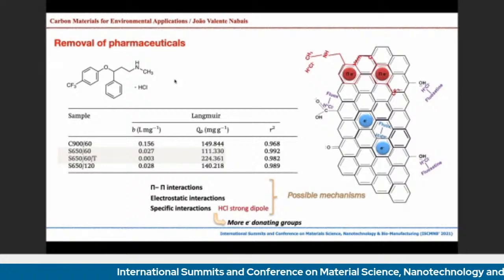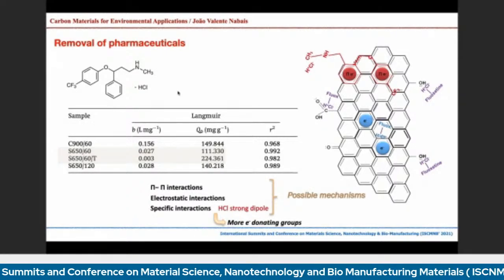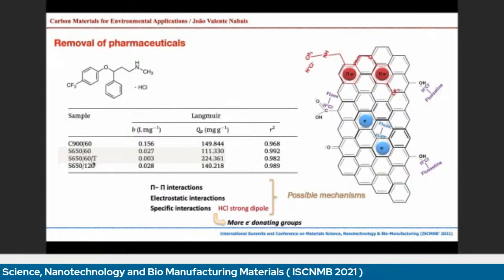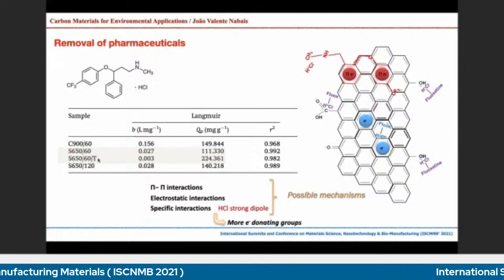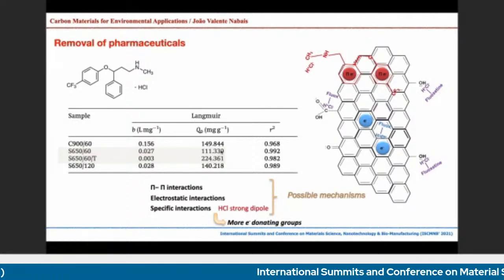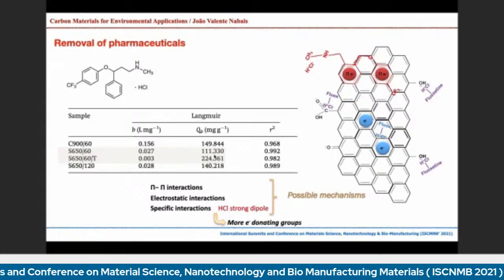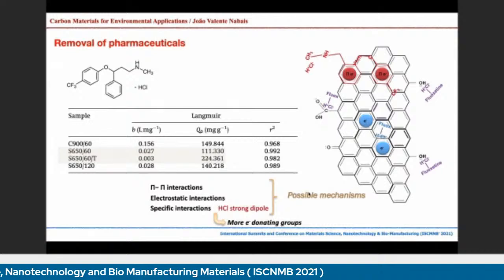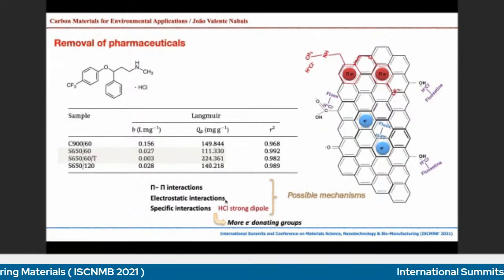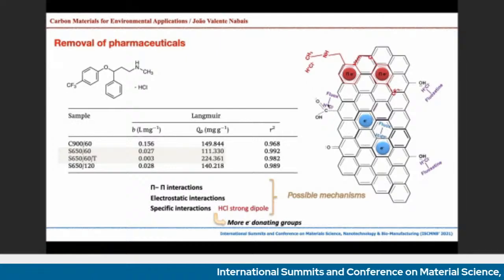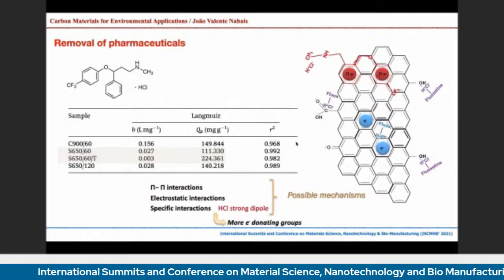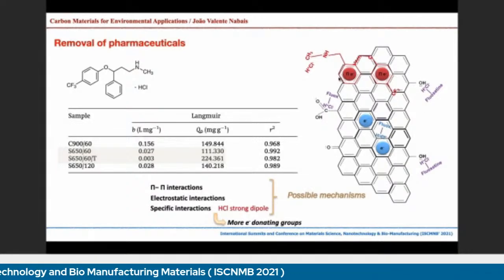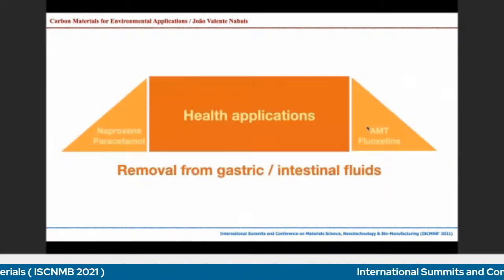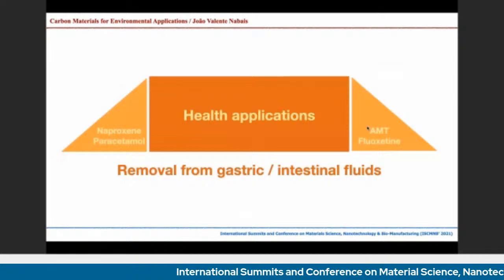When it comes to the fluoxetine, which is the principal type of Prozac, as I told you, you can see here again this T means that the material was impregnated with tether. Again, the absorption of fluoxetine has doubled. So again, the use of tether for doing the post-modification of the carbons is quite beneficial for the absorption. Here, the possible mechanisms are the pi-pi interactions, some electrostatic interactions, because fluoxetine has this group here which has a charge, and some specific interactions as well. Okay, you can see here what we think are the possible absorption mechanisms.